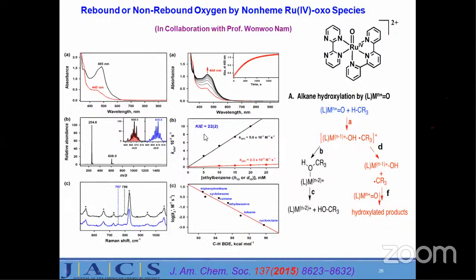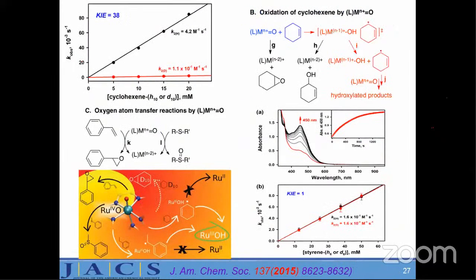When we did that, we got a large KIE, like other iron compounds. And then again we suggested the mechanism is hydrogen atom abstraction as the rate determining step. This was again substantiated by plotting the C-H bond dissociation energy versus the log k2 values, right? So this was done, and of course this work is already published in JACS 2015.